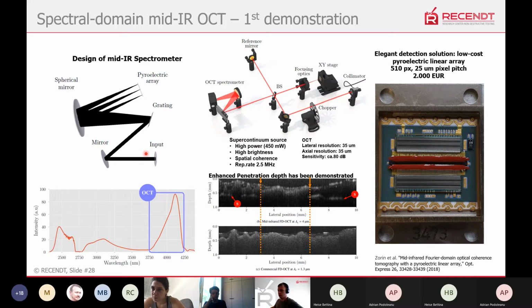Yeah, and actually it was the first or half of second demonstration, it's difficult to say, but we could already show some enhanced penetration depths into certain types of materials. So here is just the comparison of mid-infrared at 4 microns and at 1.3 microns. This is some paintings mock-ups, so it's oil paints. And usually they contain pigment particles, which makes these materials very scattering. At this time the resolution is just low because of the long wavelengths and quite limited bandwidth, and sensitivity was quite okay, I would say, but of course a lot lower than that in the near infrared range.